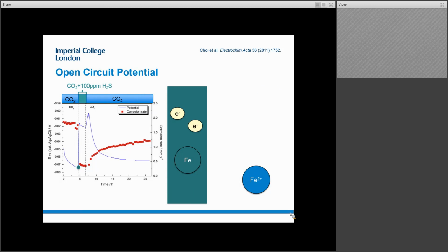But what becomes interesting at that point is you introduce H2S, at which point the authors describe an increase in the potential, and they ascribe this increase in potential as a result of the formation of an iron sulfide layer. So the iron sulfide layer is coming out on the surface, at which point they turned off their H2S, no more. They see a small jump, which perhaps can be attributed to something like iron carbonate forming on the surface as it becomes preferential when the H2S is no longer available.